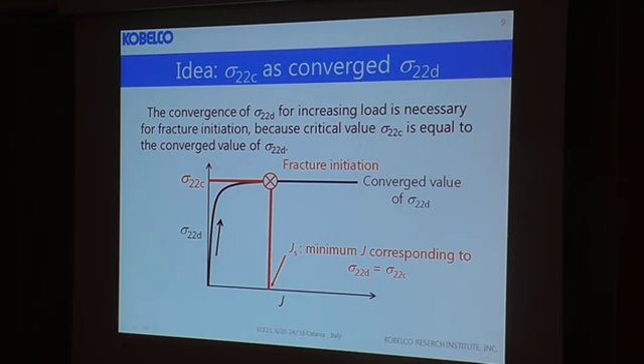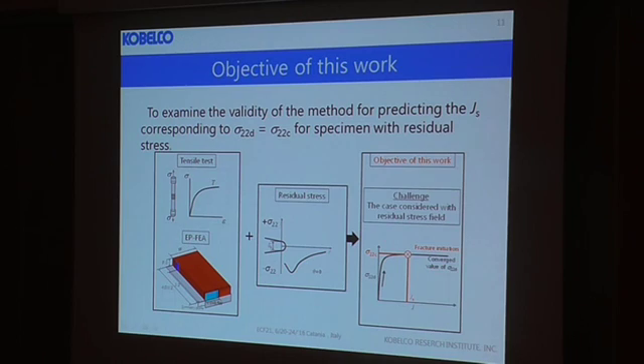Also, we expected that a minimum J corresponding to σ22d equals σ22c, denoted as JS, would give an engineering prediction of the lower bound of fracture toughness. This study is intended to examine the validity of the method for predicting JS, corresponding to σ22d equals σ22c, for specimens with residual stress by preload.